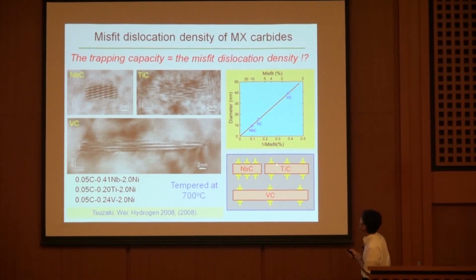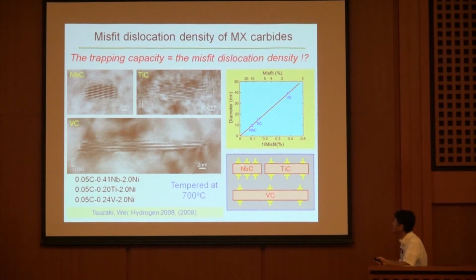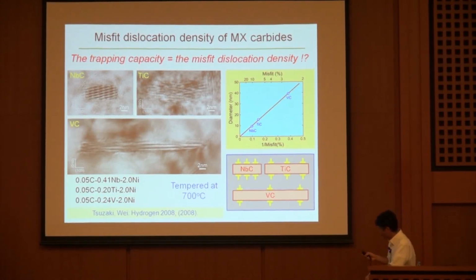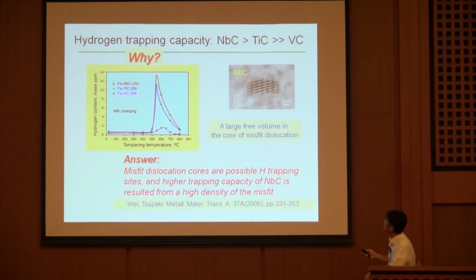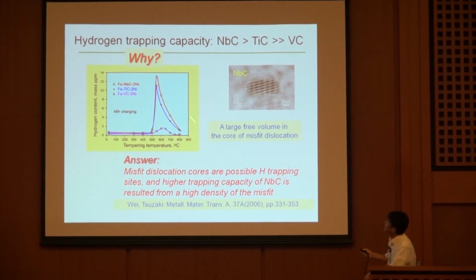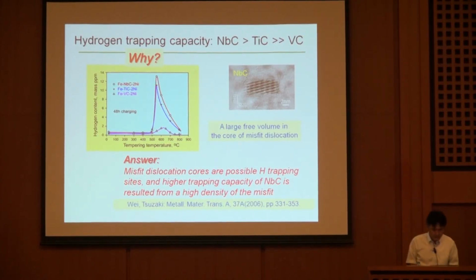And if you look at the misfit, misfit is larger in the niobium carbide and smallest in the vanadium carbide. Then the density of misfit dislocations is the highest in the case of niobium carbide. That must be the reason the hydrogen capacity changes in this order. So hydrogen trapping capacity was like this. The reason for this tendency would be that dislocations cause a possible hydrogen trapping site, and the higher trapping capacity of niobium carbide is caused by a high density of misfit.